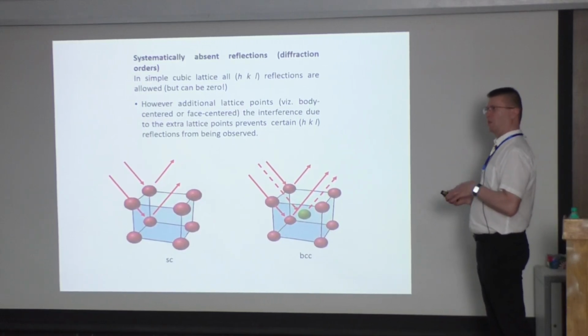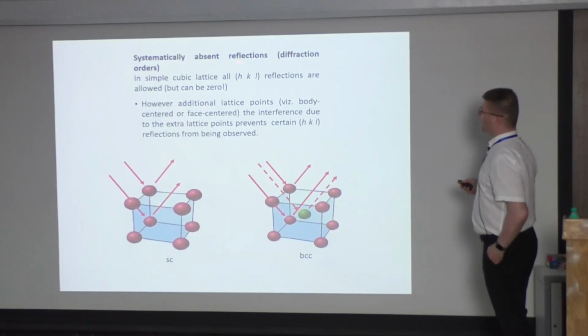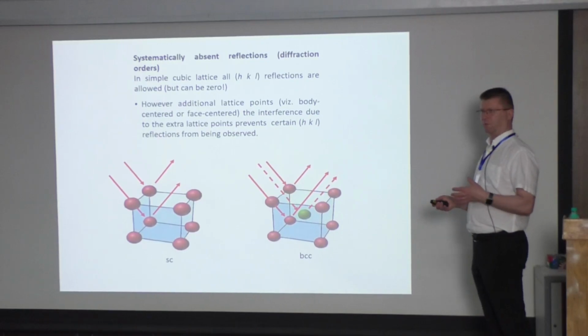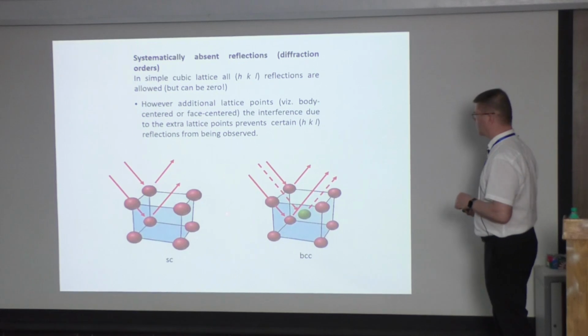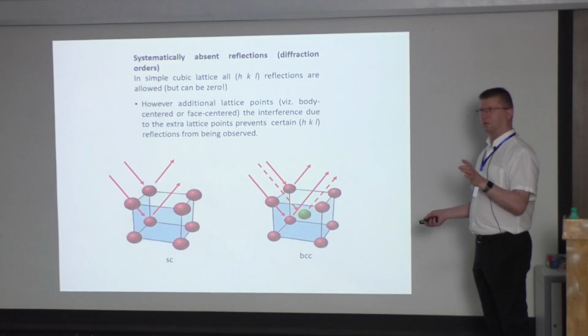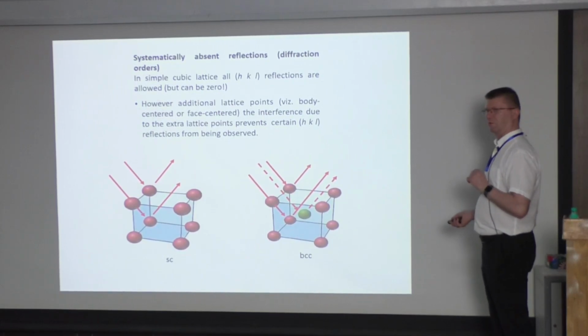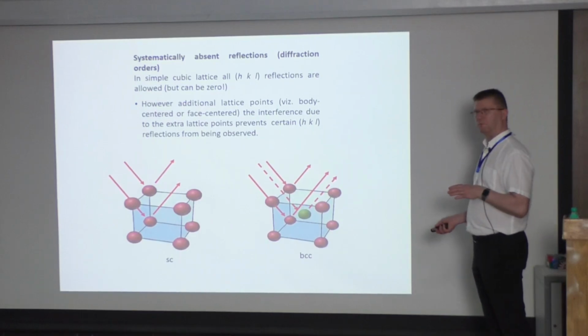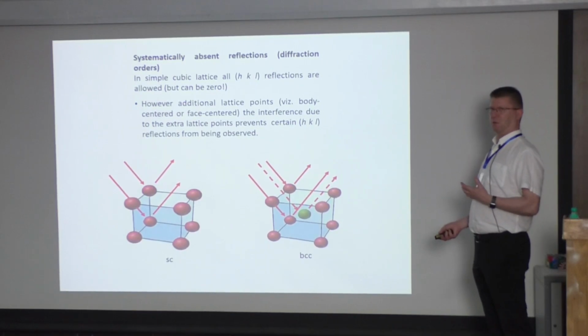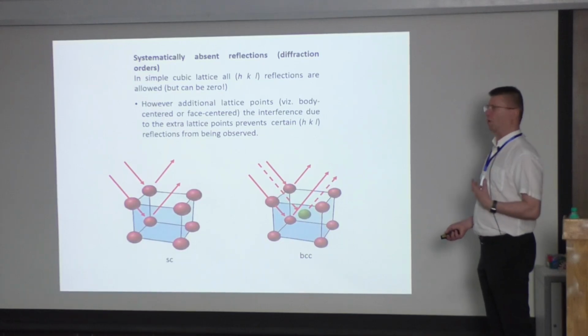Again, we are building up the house, but that is the point that it might be so that some of these HKL reflections, like by this point what I'm showing to you, might be absent, completely absent. This is an additional information for us. It tells us that, okay, we don't have now a primitive lattice. We cannot select the primitive lattice. It has to be this non-primitive lattice, or the other way around. So that is an additional information for us, or the computer program.